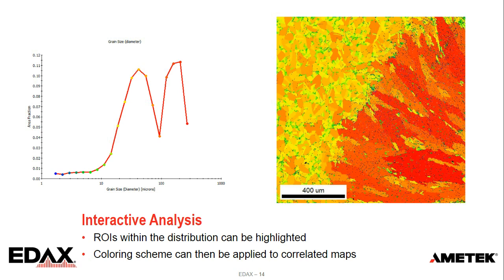The other thing I'd like to point out with this, to remember with EBSD, we have the choice of including or excluding the edge grains. You know, these grains that we see that are touching the edge, we're not measuring the full grain. So mathematically, you probably don't want to include them in your distribution. But it makes it look better to color to the edges. It looks a little weird if you throw them out. So that's why I've shown them this way. But if I'm trying to extract it correctly, I generally will exclude those.